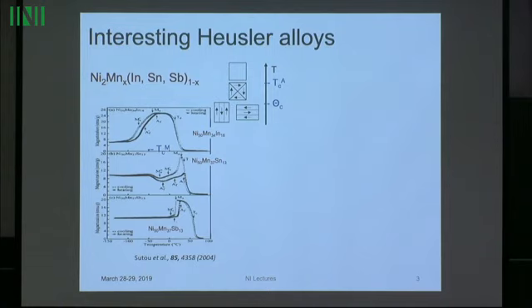This is a way you would usually see this. You would put a small magnetic field on the specimen, so actually the values of this magnetization mean nothing. It's just the transitions that you see in this kind of measurement. So this is the Curie point. That means the austenite, as you cool it, ferromagnetically orders, and then you see this martensitic phase transformation. So that has this kind of diagram.